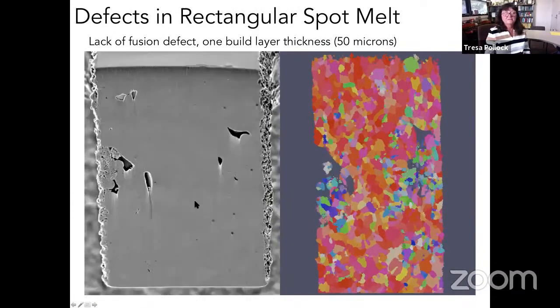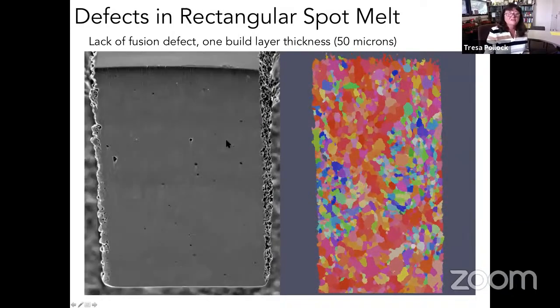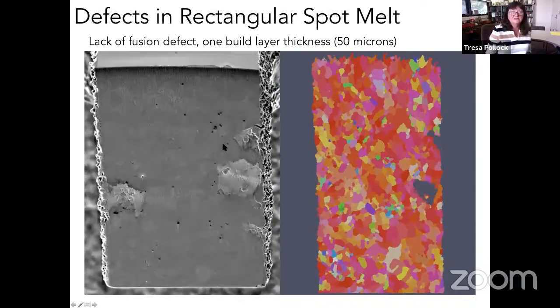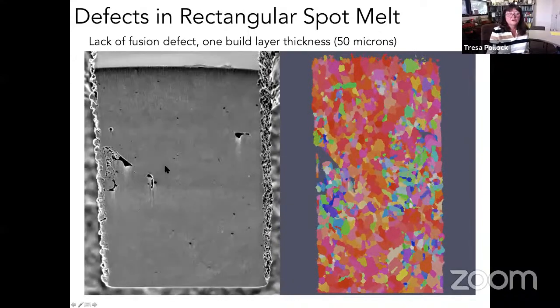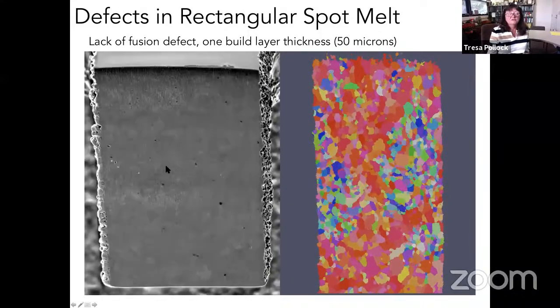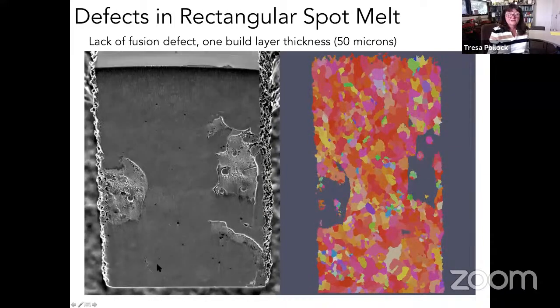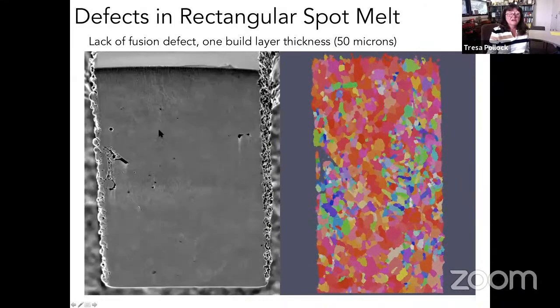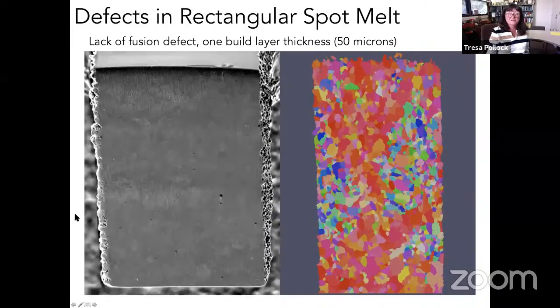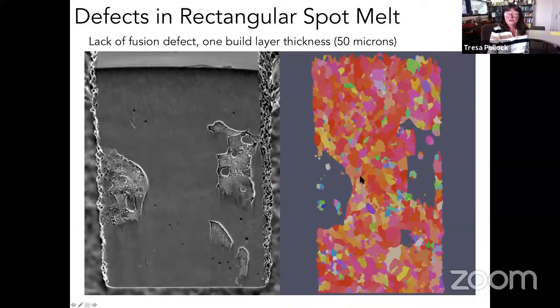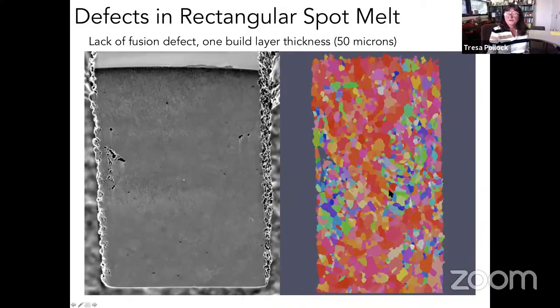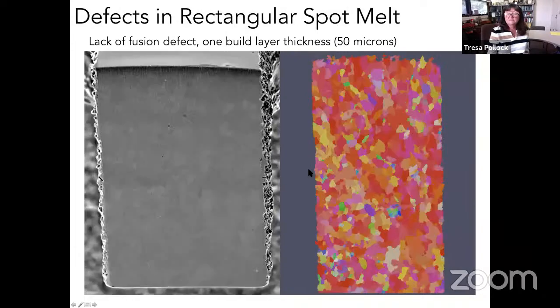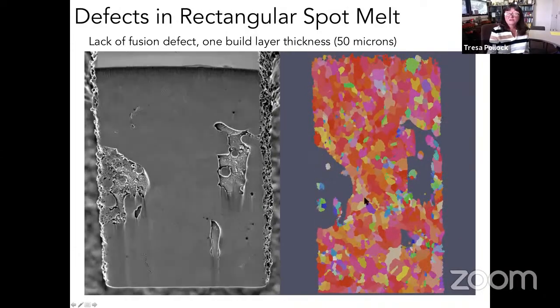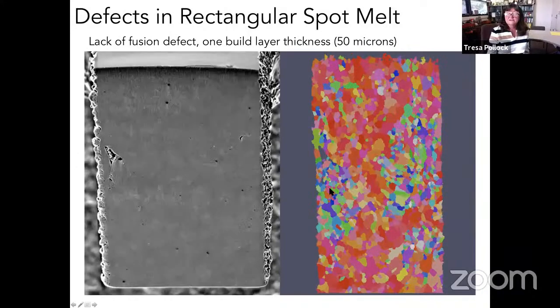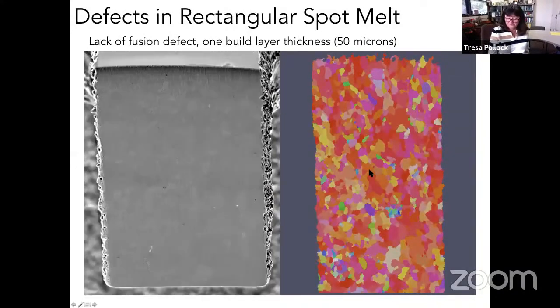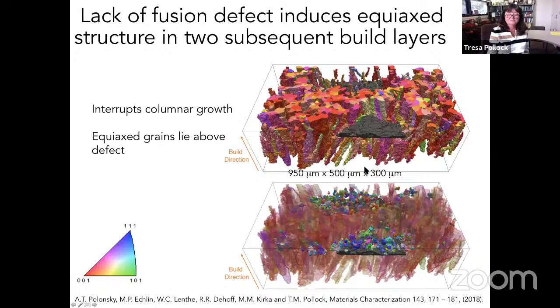Okay, this is just another example of things that one can find in 3D associated with the process. And this is one of the real challenges for using these materials in aerospace. So as we section through the material, you can see obviously there's a defect of some sort here. And if you look at the grain structure here, what you'll notice is that these defects seem to be associated with grains that have different orientations from the surrounding material.